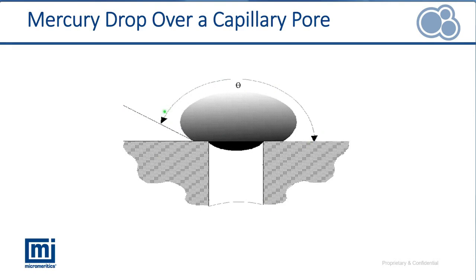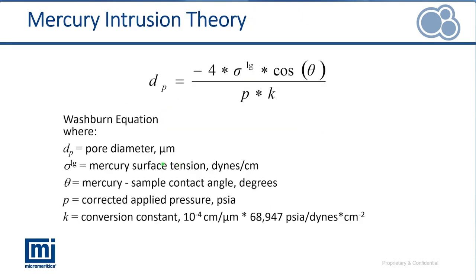Now the use of this contact angle we see here in what's known as the Washburn equation. Here we see the cosine of the contact angle being used in the calculation to determine the diameter of the pores being filled from the pressure that's being applied, also with the use of the surface tension of mercury. That is a well-known value. We just need to make sure that we use the correct value of surface tension for the analysis temperature. There is a conversion factor thrown in there just to keep all the units in the right form, depending on the common units that we're using for the parameters going into the equation, so it returns an answer to us, in this case in micrometers.